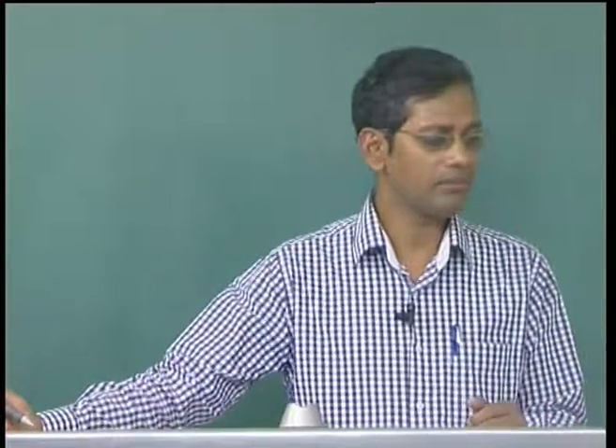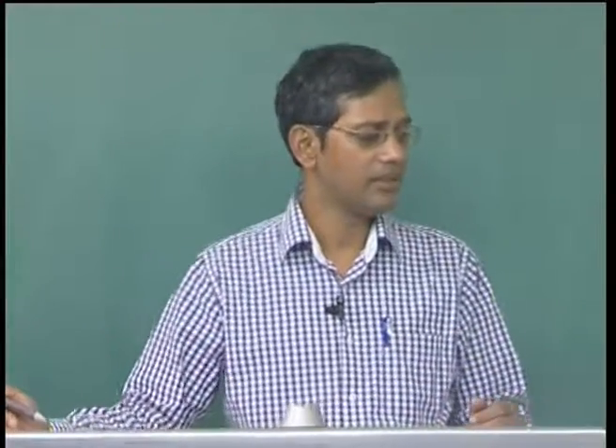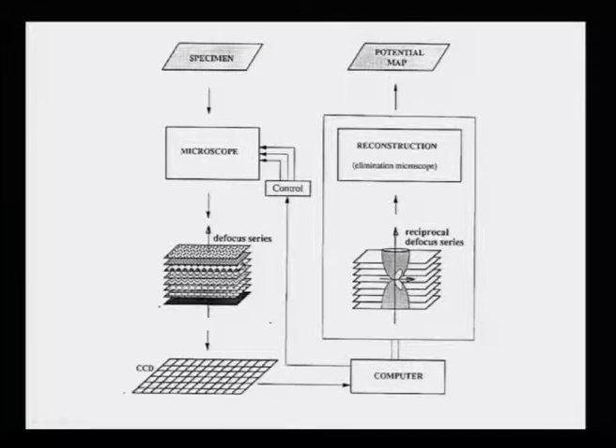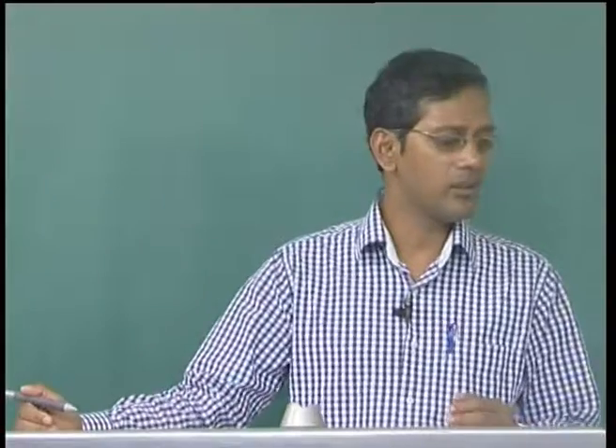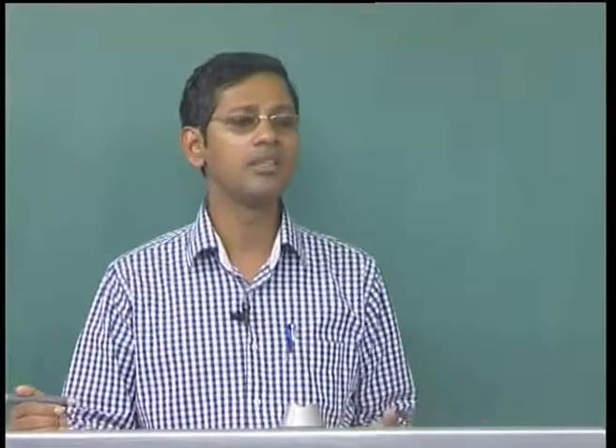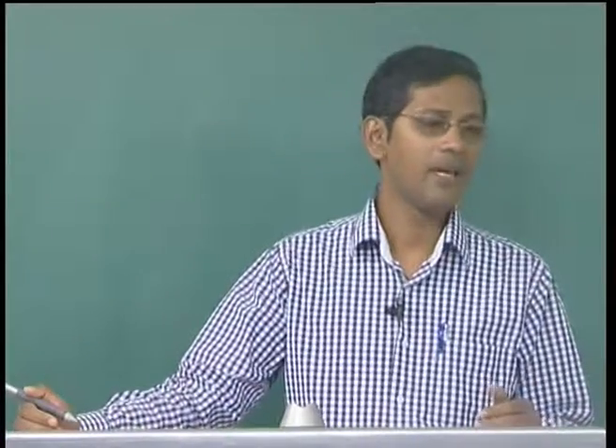Input to the multi-slice method must contain different parameters of the specimen: the unit cell, the positions of atoms inside the unit cell, the Debye-Waller factor due to atomic vibration with temperature, the orientation of the specimen or crystal, and the thickness.